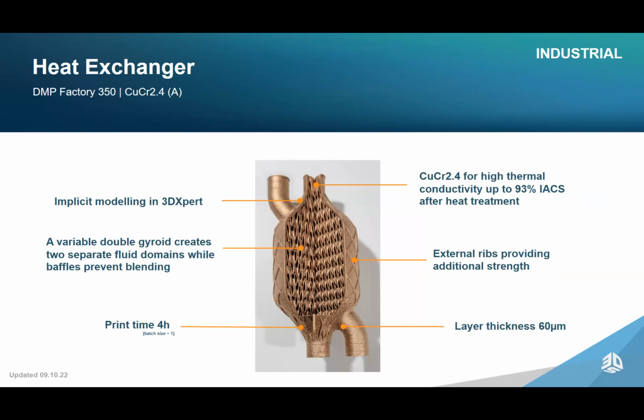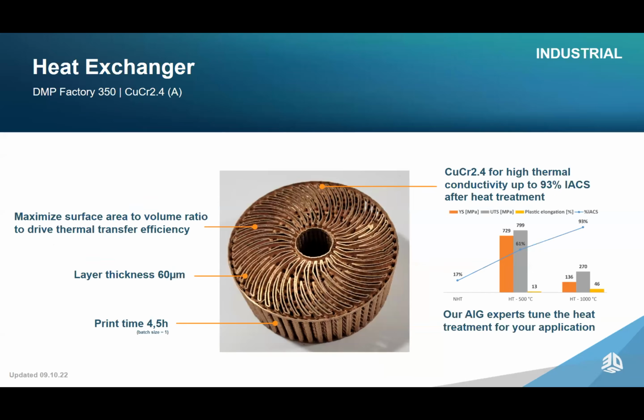Going to be a good application for copper chromium, CuCr2.4, copper chromium zirconium. Something a little bit more stable than just pure copper, which is pretty ductile. This was implicit modeled in 3D Expert. For this specific one, we're up to 93% IACS. Again, it's geometry dependent. And yeah, this is printed in 4 hours.